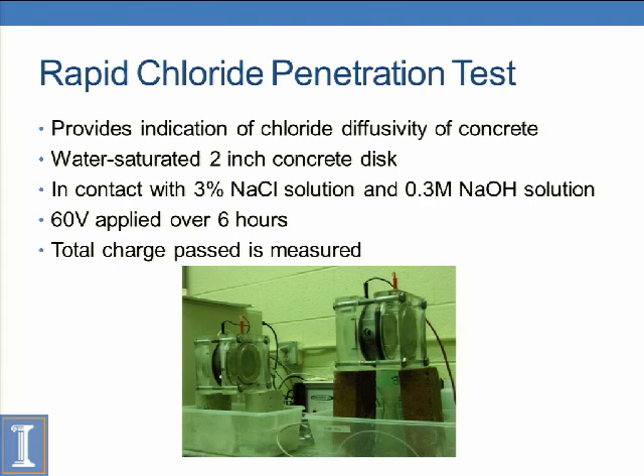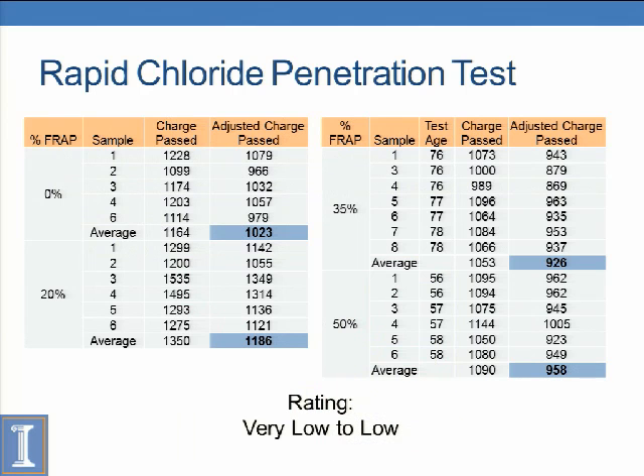And pretty much we have a test set up. You have a machine that will measure the charge passed over a 6-hour testing. And pretty much what we get from that is, from these ratings, the average is all about around 1,000 for each of our FRAP contents. And that correlates to a rating of low to very low permeability, is typically what people say, or penetrability, if you will. Just in terms of this test, if you have a concrete that's more on the scale of 2,000 to 4,000, you have a higher permeability concrete. So this concrete at 56 days has a low to very low permeability, which is very good for us. And that's probably mainly due to the slag and fly ash we used. If it was plain cement, these ratings would probably be higher.